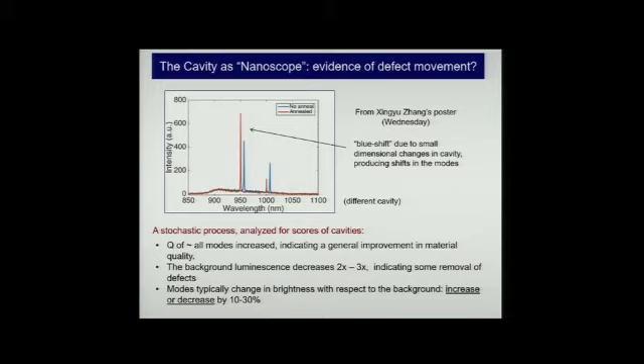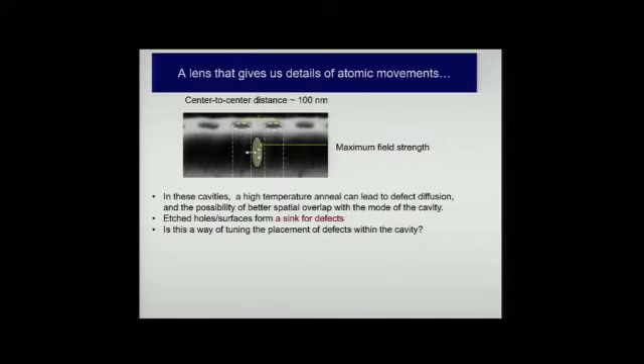But here's another, this is a picture that actually overlays them, and there's a slight shift between no anneal and anneal, because actually, when we do the anneal, we slightly oxidize the cavity. These cavities are so sensitive that their resonant frequencies change. But you can see even more clearly here the change in intensity. And that is actually where I'm going to close, but this is where the exciting part is, and this is the part where Tim and Roderick have been helping us enormously.